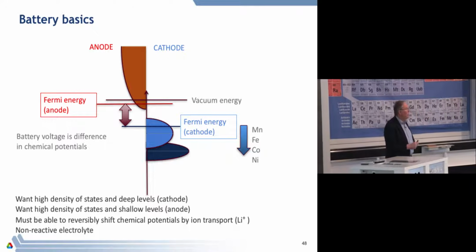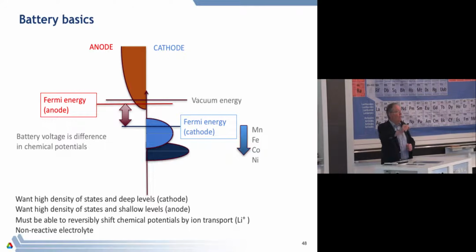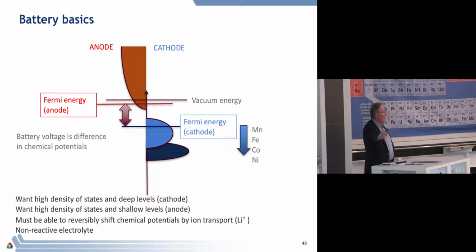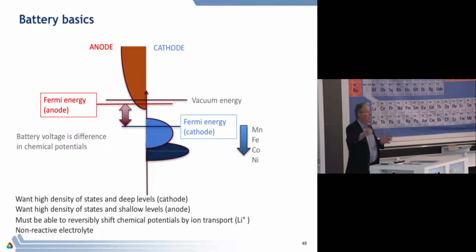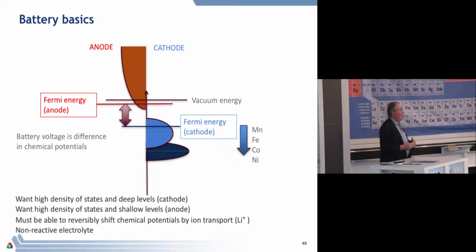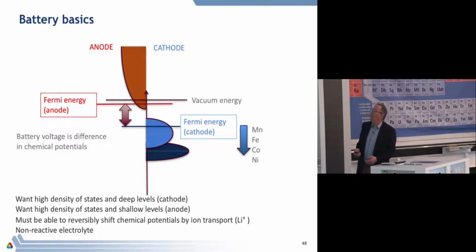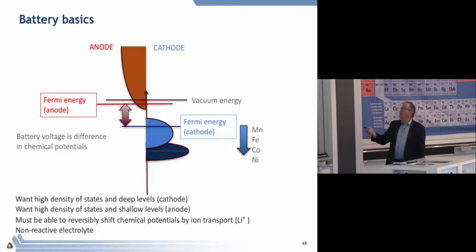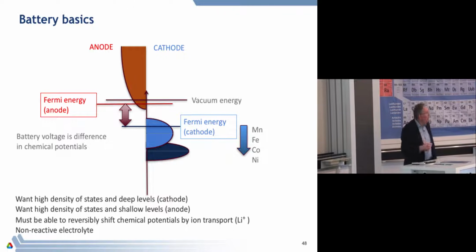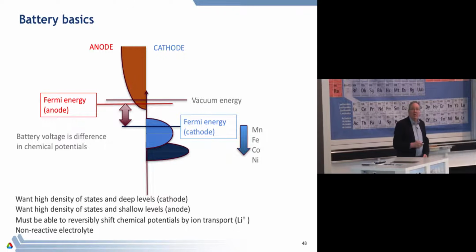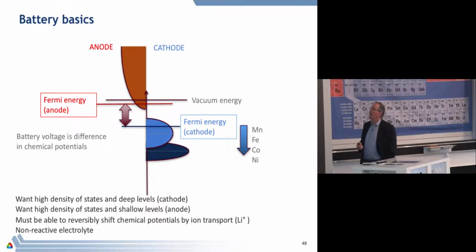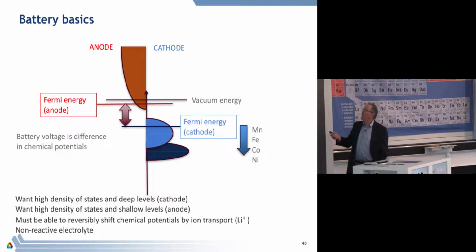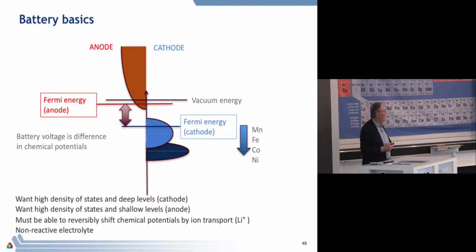So if I'm working with a 3D transition series, that tells you go all of the way to the right, because as you go to the right-hand side of the D transition metal series, the D levels move down. That's the contraction that happens as I go across any series. So you'd actually like to go from manganese to iron to cobalt to nickel. And if you look at battery technologies as they've advanced over the last few years, that's exactly what people have tried to do.